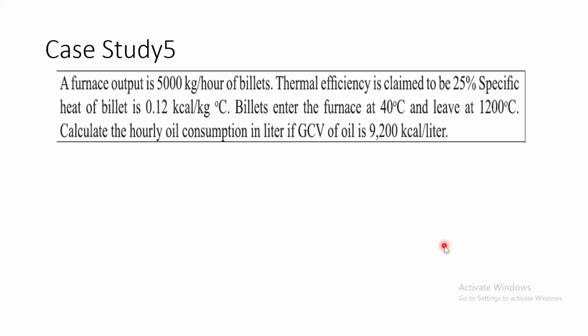A furnace output is 5000 kg per hour of billets. Thermal efficiency is claimed to be 25%. Specific heat of billet is 0.12 kilocalorie per kg degree centigrade. Billet enters the furnace at 40 degrees centigrade and leaves at 1200 degrees centigrade. Calculate the hourly consumption of furnace oil in liter if GCV of the oil is 9200 kilocalorie per liter. I think this problem is not at all difficult. If you have any difficulty, sir, please ask me.